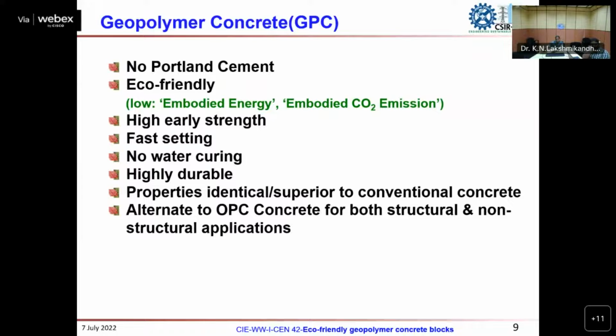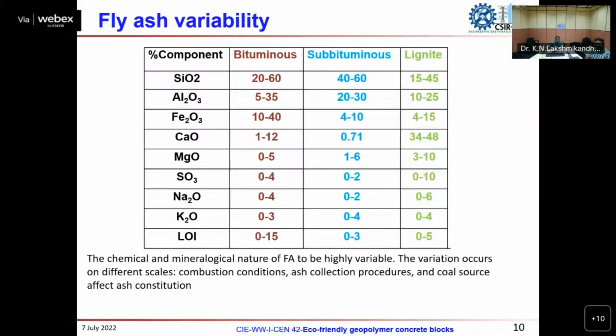Geopolymer concrete of grades from M5 to M150 has been developed at CSIR SCRC. It is fast setting, because most of the time in 14 days itself around 90 to 95% of the 28 day strength is achieved. After that, there is not much improvement. Also, no water is required for curing. It is highly durable, and we have studied both structural aspects as well as non-structural concrete components using geopolymer.